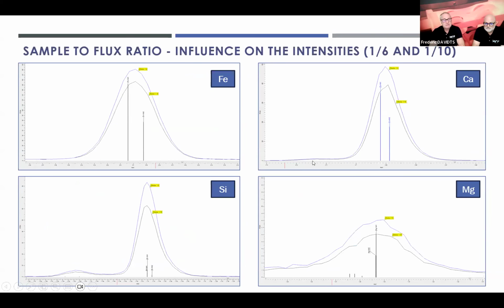What we can see here now is 2 different sample preparations, a 1 to 6 and a 1 to 10 dilution for 4 different elements. Iron being a heavier element and magnesium being the lightest element. So we can see when we use a dilution ratio of 1 to 10 that we have less intensity than when we are using a 1 to 6 dilution ratio. And this is true for all the elements. So we must be aware when we use a higher dilution, we have lower intensities, and therefore for some elements we may not be able to analyze them anymore because the concentrations become too low.